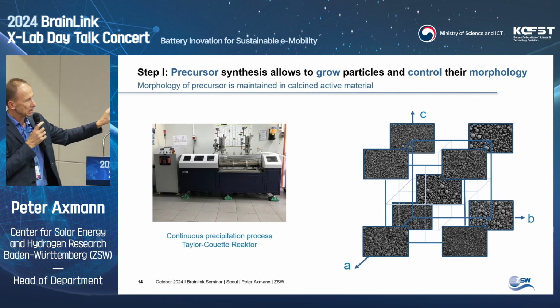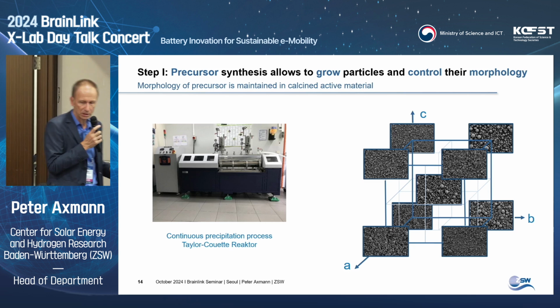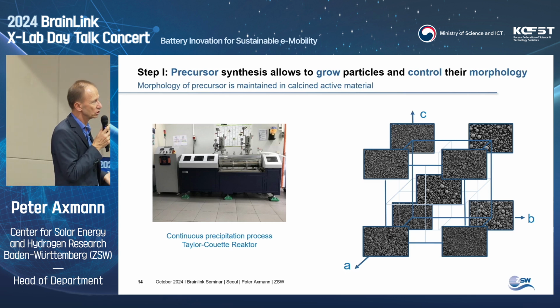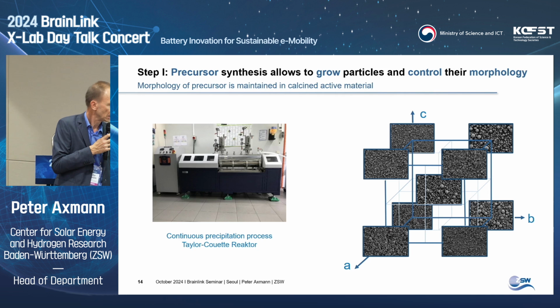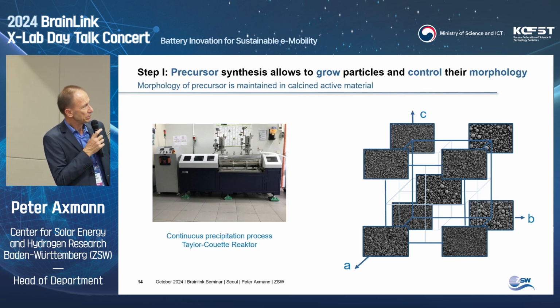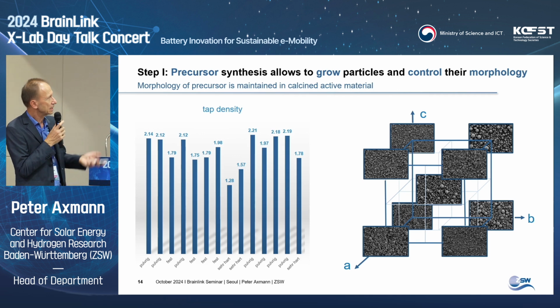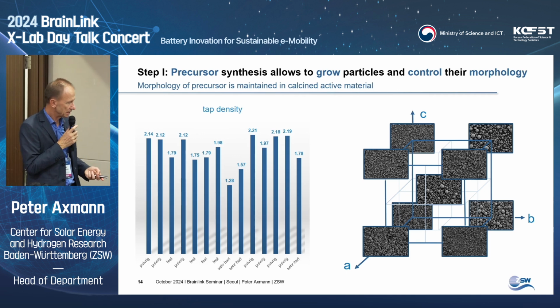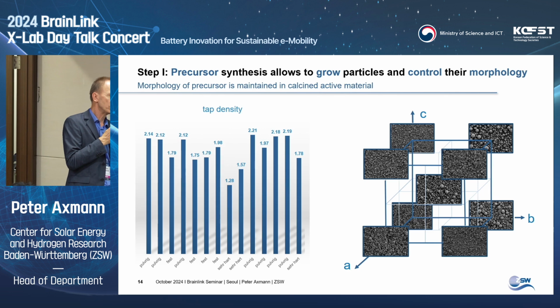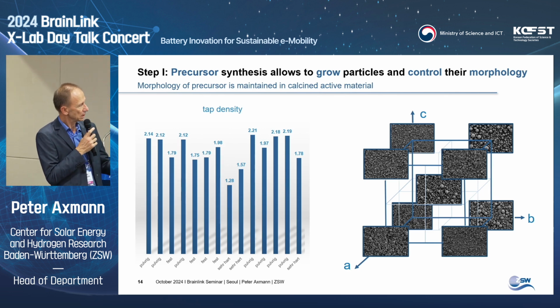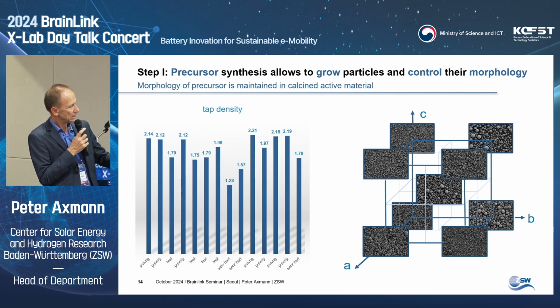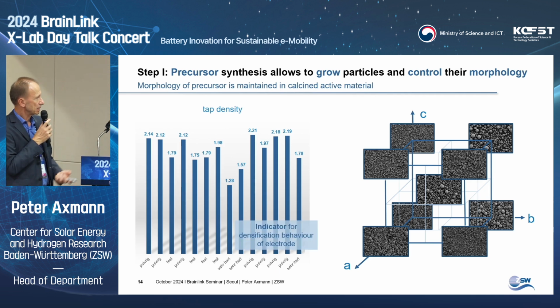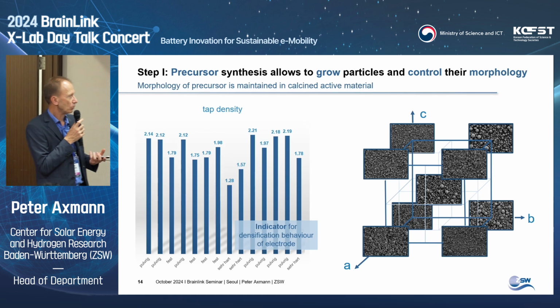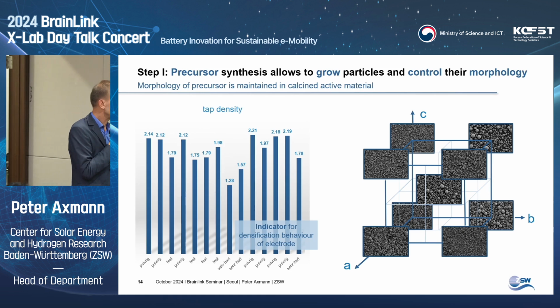And if you go beyond this scale, you reach even gel-type materials which you cannot filtrate anymore. So nothing which you can use then for technology. But the spherical shape, or the shape of the materials, is not all. There are some factors, for example, the tap density, which changes as well. And the tap density is more or less what you reach if you tap a material very often. How dense can you pack the spheres you obtain here? And this tap density is an indicator of how much you can densify the electrode later.